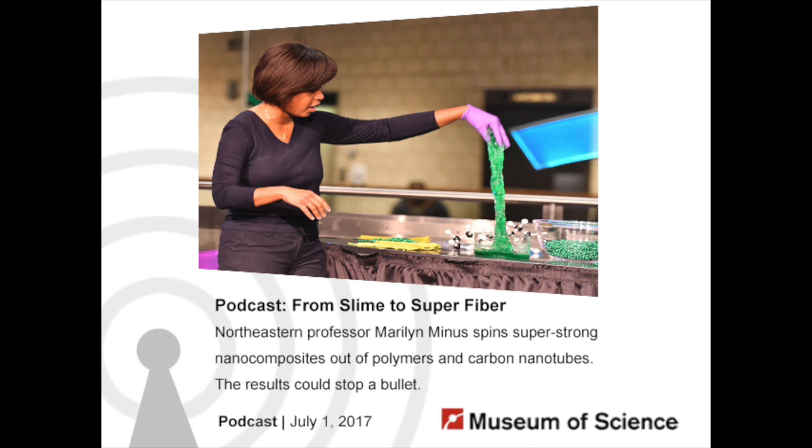We know that if you pull on the polymer chain, lining it up, then it automatically is stronger than if it was sliding next to each other. So it's always the case that aligned chains are stronger than tangled chains. But how strong that polymer is will depend on its chemistry. So not every polymer is going to be super strong, but most polymers are made of carbon, and that carbon-carbon bond, the same bond that makes nanotubes, is a very strong bond. So carbon-carbon backbone chains are the chains that will be the strongest materials, but other polymer chains out there can be stronger than they currently are, but they may not be the strongest.